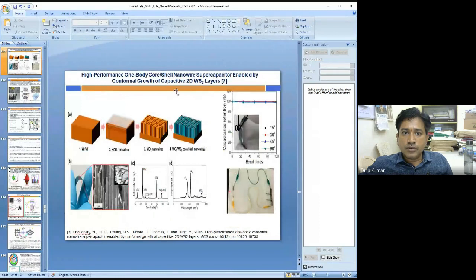Now, what we call tungsten sulfide layers. This is also one form of a novel material where tungsten is exploited with sulfide groups, TMDs. This is a high performance core shell nanowire supercapacitor, which is made up of tungsten sulfide layers, and which was published, in 2016, in ACS Nano. So the synthesis is a general synthesis. The only thing is we can manipulate, optimize, and extrapolate to get the required structures.